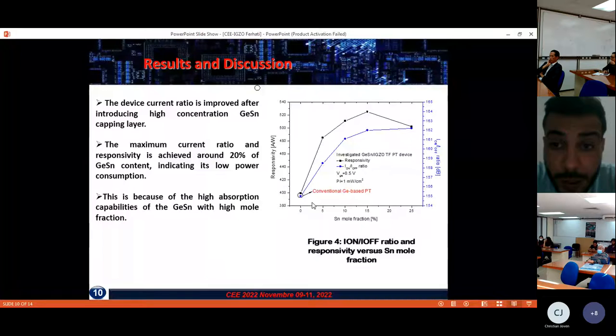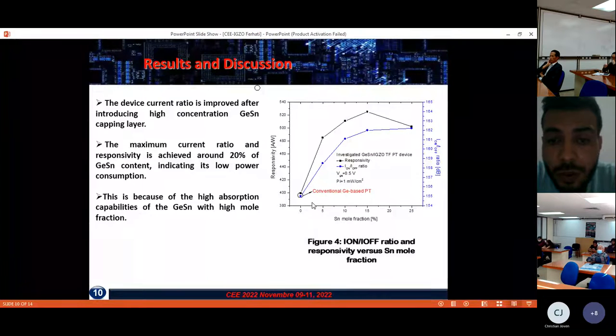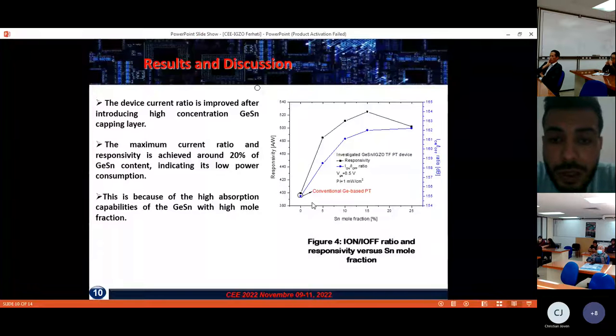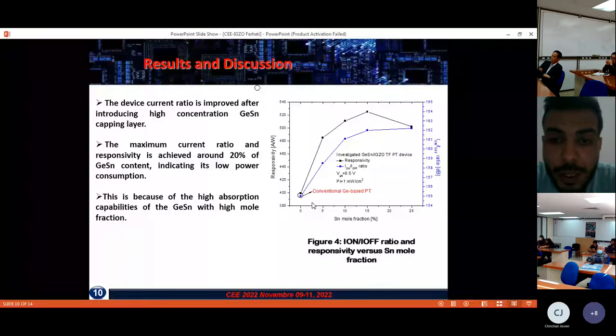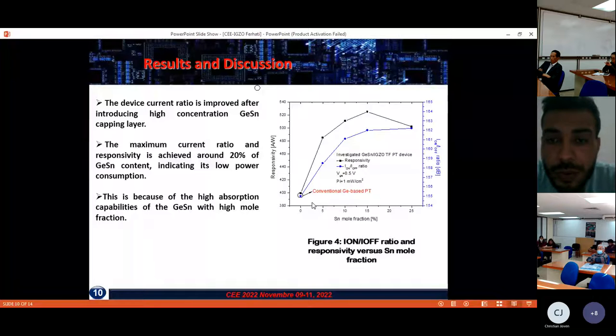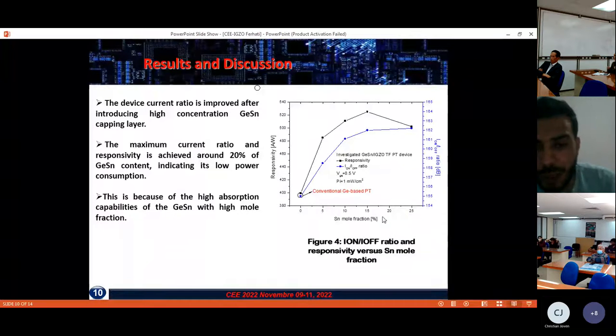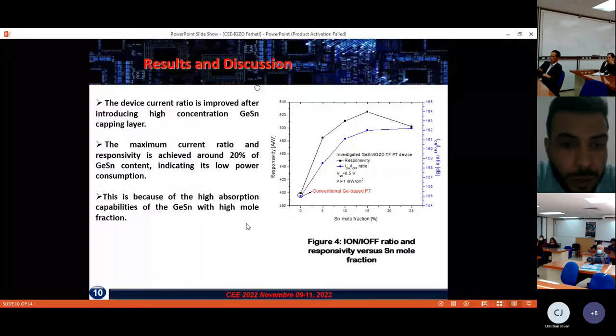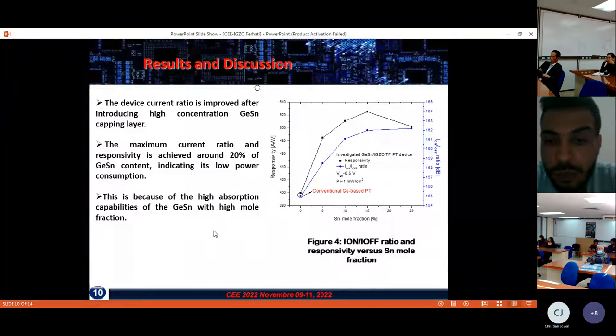To analyze the effect of the tin mole fraction on the sensing capabilities of the device, this figure shows both current ratio and responsivity as a function of the tin mole fraction. It can be seen from this figure that the device responsivity and the current ratio increase with the Sn mole fraction increase until achieving the highest value for a tin mole fraction of 15%. This is because of the high absorption capabilities of germanium tin with high mole fraction.